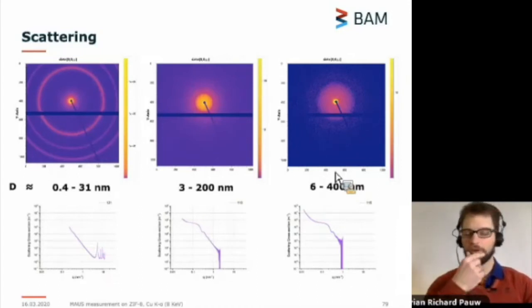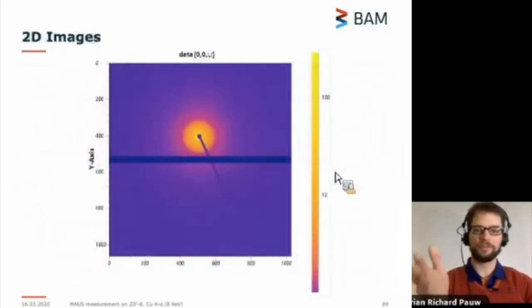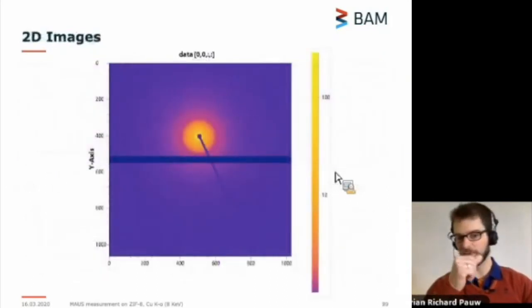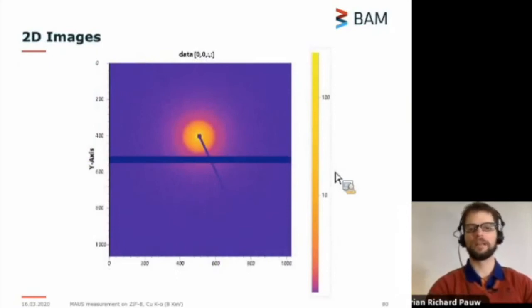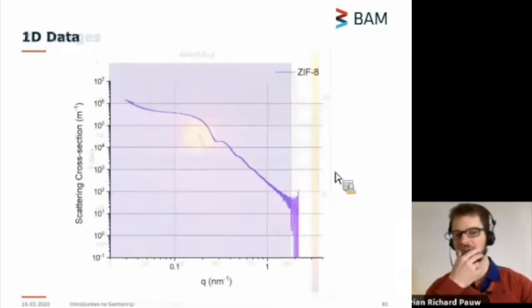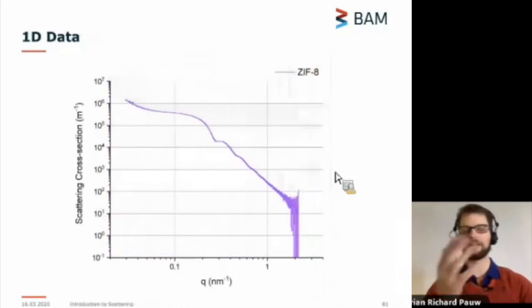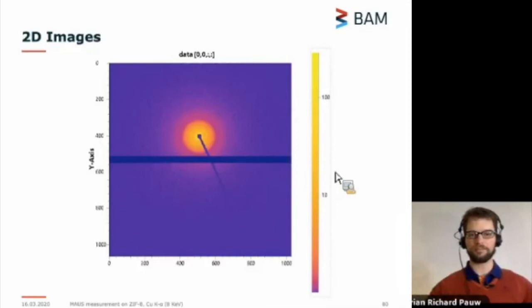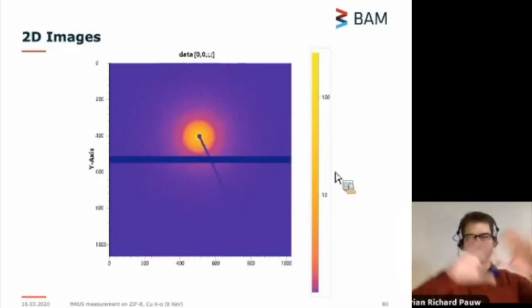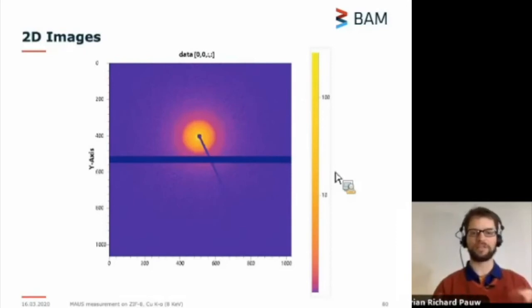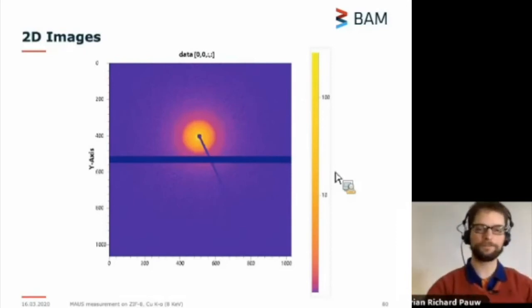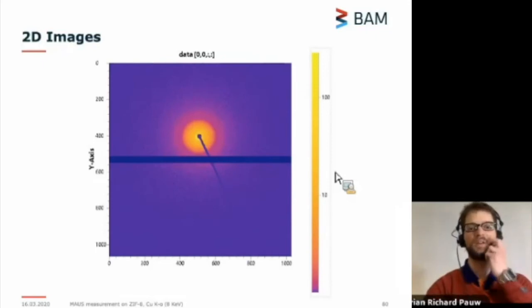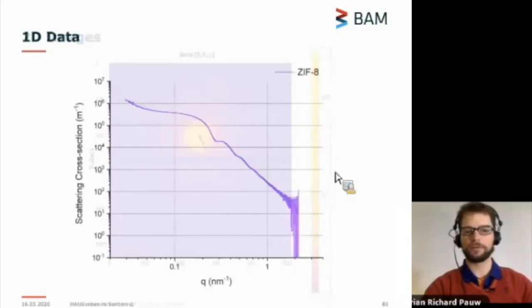You see that we often go from two-dimensional scattering images like this to one-dimensional curves. We can do this in case this two-dimensional image is not oriented. So in case we don't have an oriented structure in our sample, with structures pointing all in one direction, if everything is randomly oriented, they scatter in all directions equally. And that means we can do this azimuthal integration, which looks like this.